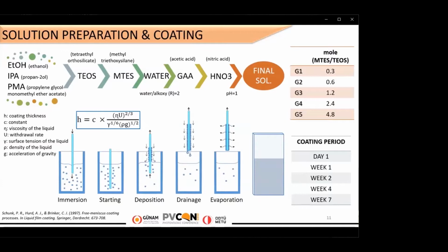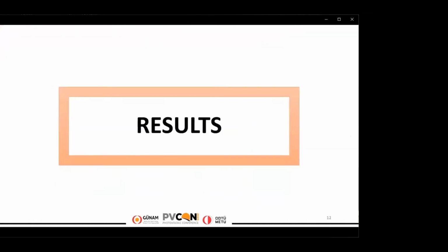The most important parameter is withdrawal speed, which you can see in the equation. The withdrawal speed determines the thickness of the deposited film. A higher speed produces a thicker film. As I mentioned before, our withdrawal rate was 150 millimeter per minute. With this method, we coated our samples with the periods you see in the table and examined the effects of the waiting time of the solution. Let's continue with results.